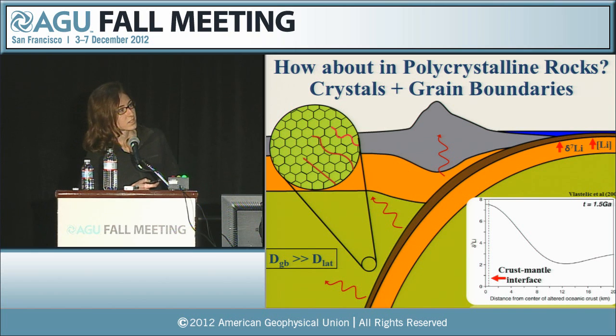So one way to shed light on this issue is to look at the altered subducted slab and the mantle as a diffusion couple. This is one such example of that by Vlastelic et al. In this graph, we see delta-7 lithium as a function of distance from the center of the altered oceanic crust, and the crust-mantle interface is shown by the dotted vertical line. These authors conclude that after 1.5 billion years, there's still a lithium isotopic heterogeneity that is able to survive that long. What these models are very highly dependent on is the diffusivity of lithium that they input into their models, as well as the beta factor. So that's what we set out to find.